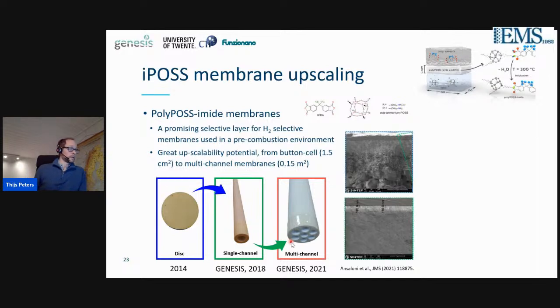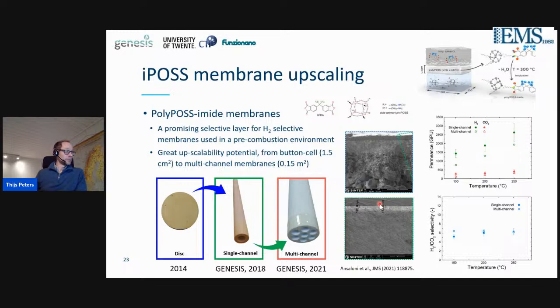Here you see the cross-section of the single channel membranes, where the very thin polyimide membrane layer, which is made by interfacial polymerization, is applied on top of the asymmetric membrane support, consisting of an alpha alumina and typically a gamma alumina intermediate layer. The actual layer you don't see in this picture, but it's around 100 nanometer thick. And the main result of this work was that the performance of the multi-channel membranes represented very well the performance that was obtained on the disc membranes at the start of the project.